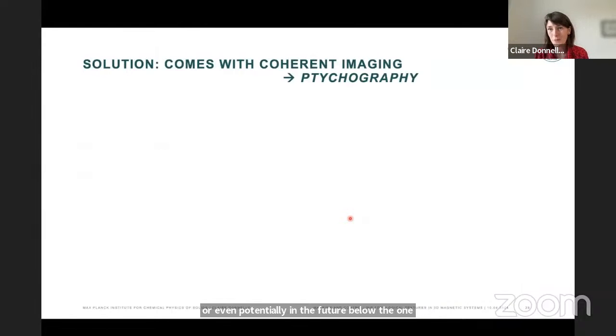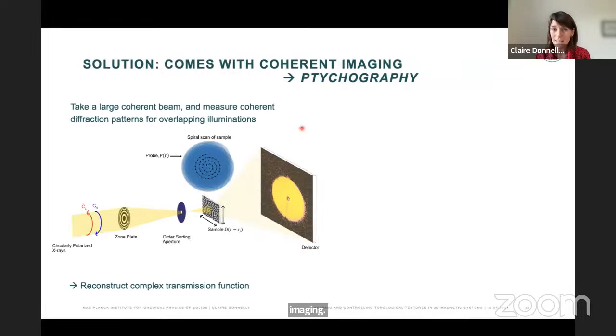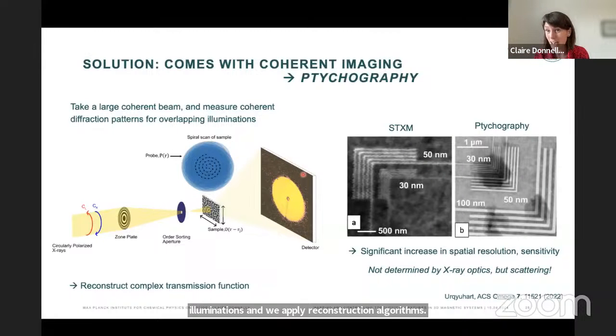The way that we can do this is to go towards coherent imaging, such as ptychography. The idea here is that we take a coherent beam, and rather than nanofocusing our beam, we take a large beam where we measure coherent diffraction patterns in the far field for overlapping illuminations, and we apply reconstruction algorithms to recover high spatial resolution and highly quantitative images of our sample. And now immediately you see in this nice comparison, ptychography on the right and STXM on the left, that because we're not limited by the lenses, and you have really quantitative data, you can get beautifully high contrast and high spatial resolution imaging of your systems.